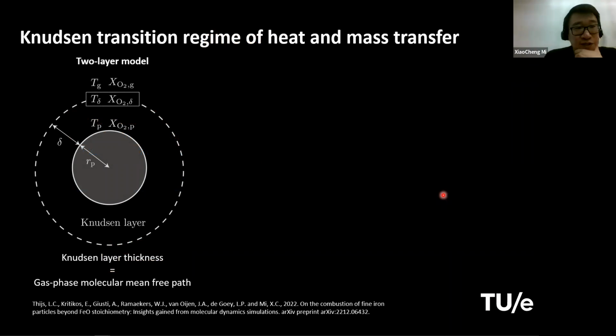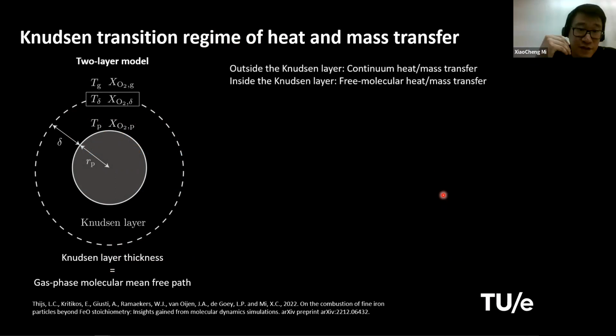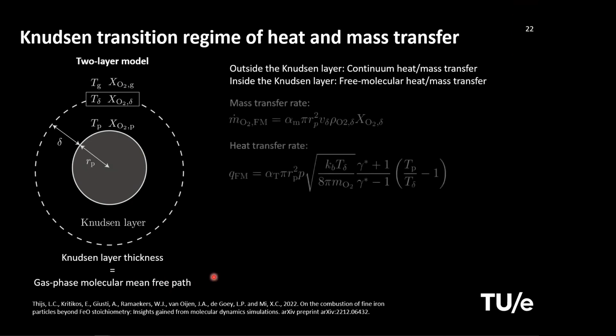And to consider the transition regime of heat and mass transfer, we take this paradigm that has been used in the literature, which is the two-layer model. In the inner layer, the so-called transition layer, the heat and mass transfer is governed by the free molecular regime mechanism. And outside this layer, we still apply the continuum heat and mass transfer model. The thickness of this layer is equal to the gas phase molecular mean free path, which can be calculated as a function of the boundary layer temperature.